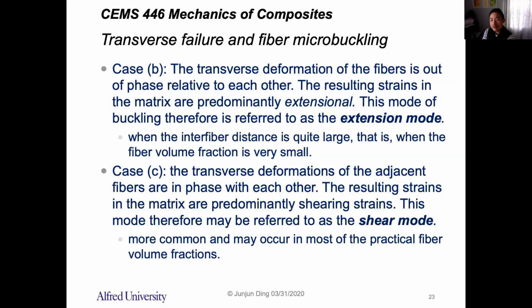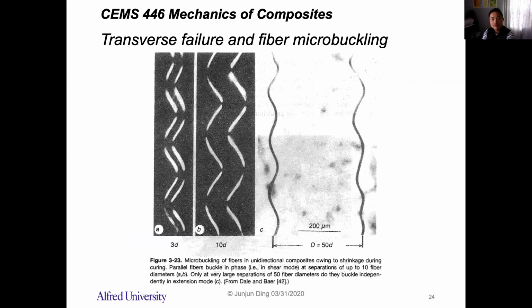And in the case C, right? If you have a higher volume fraction of the fiber, the transverse deformations of the adjacent fiber are in phase with each other. So the resulting strains in the matrix are predominantly shear strain. So that's why this mode is called a shear mode, right? It depends on the deformation of the matrix.